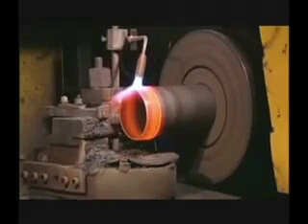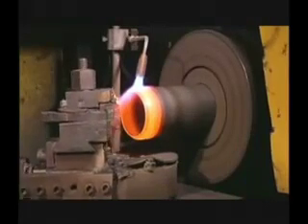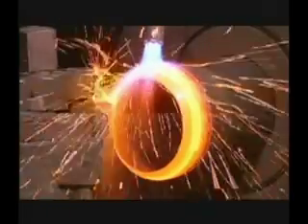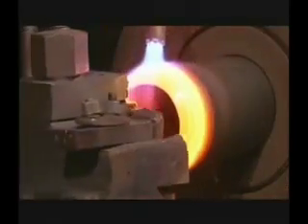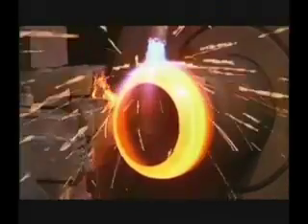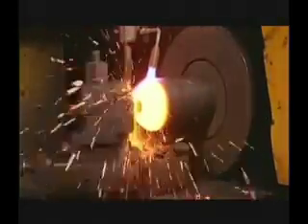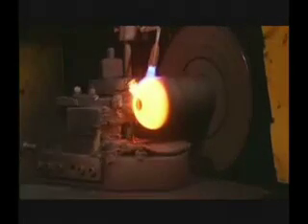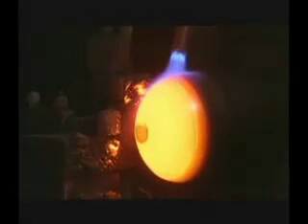It is placed into a spinning lathe that operates at about 1000 RPM and is programmed using CNC technology. Using synchronous movements of 2 axes, the machine gradually forms the shoulder and neck areas of the cylinder. The hot spinning process must be carried out with care and expertise so that folds or other defects are not introduced into the neck area of the cylinder.